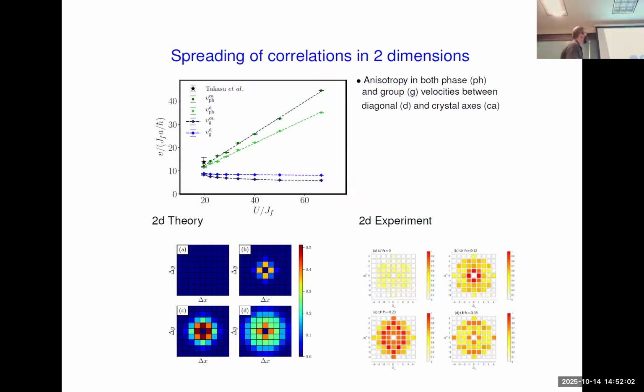If we go to 2 dimensions, again, we can calculate the phase and group velocities. And here we differentiate between the spreading along the crystal axes and along the diagonal. We see that these 2 are different. But we also see that our results are compatible with Takasu et al.'s experimental results.